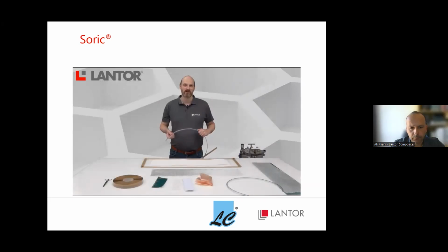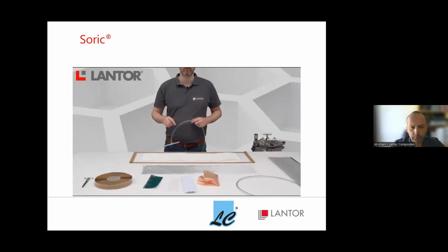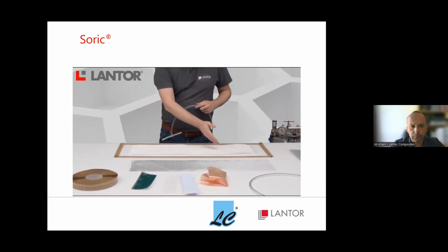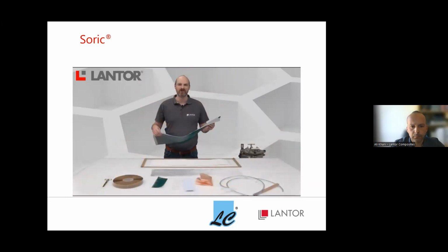Next, we plan out our vacuum and resin infusion lines. The most robust thing to do would be to infuse along the shortest distance, which would be the width. On a large surface, the resin feed line can even be placed on top of the layup. However, in order to demonstrate the resin flow capabilities of Soric, we will be infusing along the length of the layup. Traditional vacuum infusion will require a flow mesh to facilitate penetration of the resin into the materials, and an equal length of peel ply to remove the flow mesh after the resin is cured.